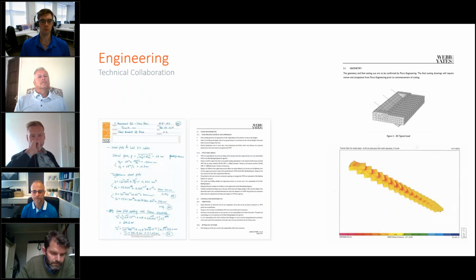The critical test driving the stair design was compressive strength. Preliminary design determined that the minimum value required was 113 MPa, with average results coming in at 188 for both wet and dry conditions. Density or bulk specific gravity, ASTM C170, was another key confirmation, which would feed the load criteria, and tests indicated 187 pounds per cubic foot for this. Absorption, C97, was also done, but less impactful for our interior application. All tests performed well with very small variances, which confirmed the consistency that we wanted. A threaded rod pullout test was also performed for assessing guardrail design.